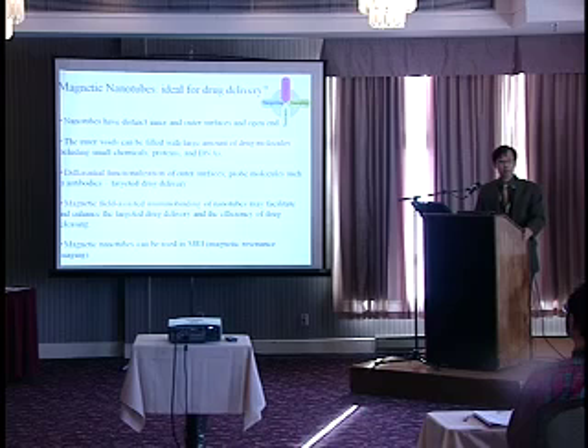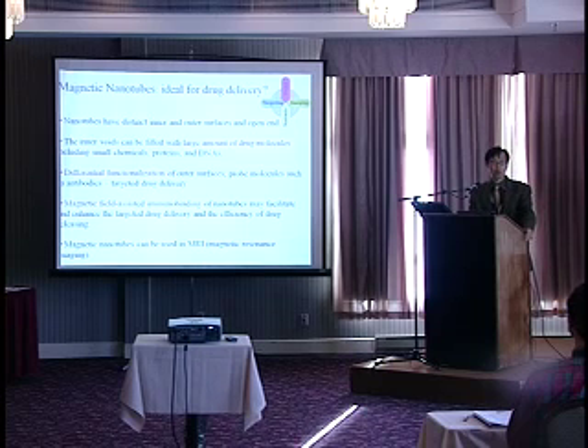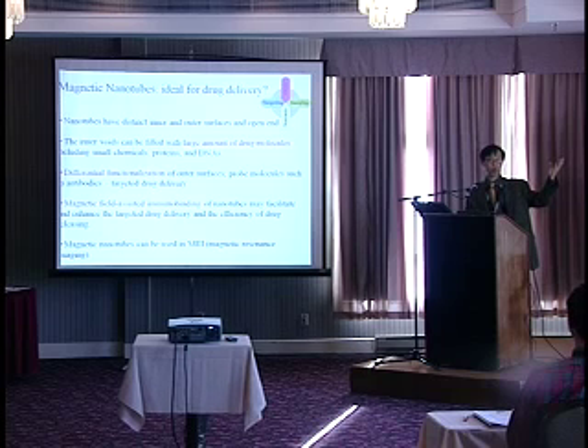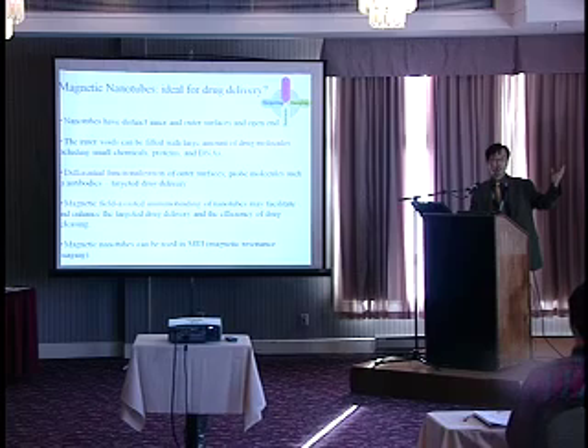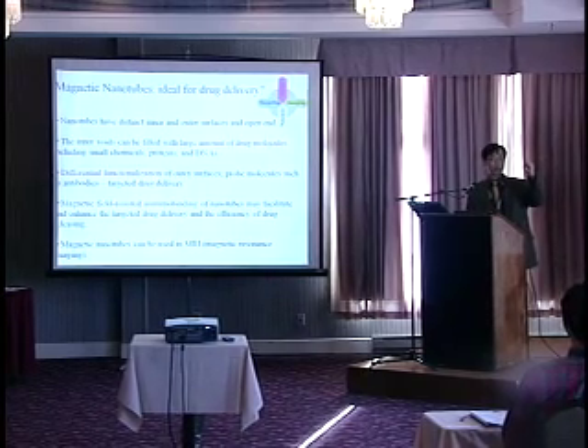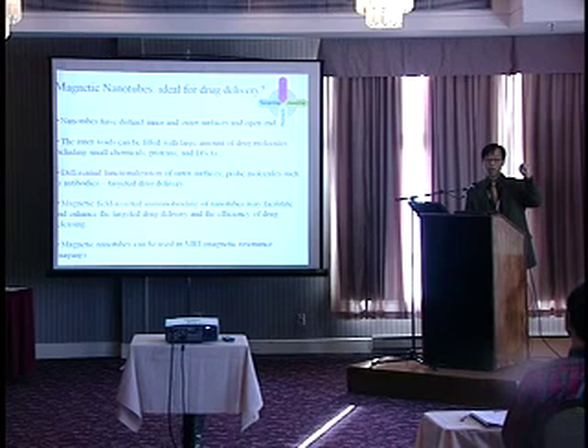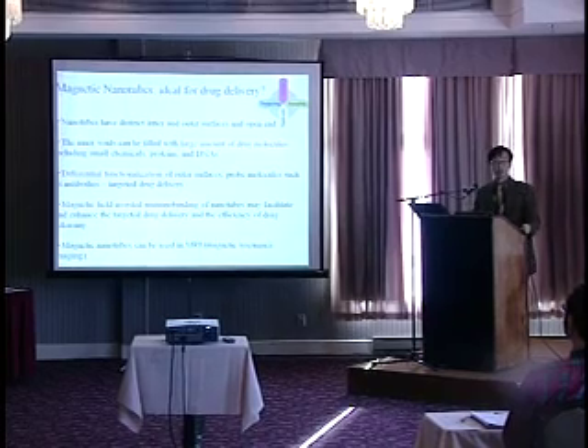One of the good reasons is that many drug molecules, especially cancer drug molecules, are hydrophobic. So imagine that you have those hydrophobic drug molecules on the outer surface of nanoparticles, and if they cover more than 20% of the outer surface, then this nanoparticle is no longer really hydrophilic. And they will change its surface property dramatically. And this nanoparticle is likely to stick pretty much everywhere through nonspecific hydrophobic interactions. So there is a good reason why you need to hide and separate those hydrophobic drug molecules inside the particles and keep the outside surface hydrophilic and also environmentally friendly.